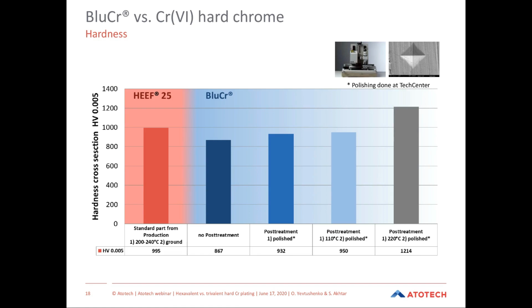So the next important point, what about hardness? Chromium is very loved for this property, hardness. Here you can see again the comparison of layers deposited from BluCr and HEEF 25. At this point, I have to admit that if you compare hardness, you need to be sure that you compare hardness measurements done by the same method. In this case, the hardness was measured on a cross section. For that, the layer thickness must be big enough. And you can see that the layers deposited from BluCr are in fact a bit softer if you compare with HEEF 25.